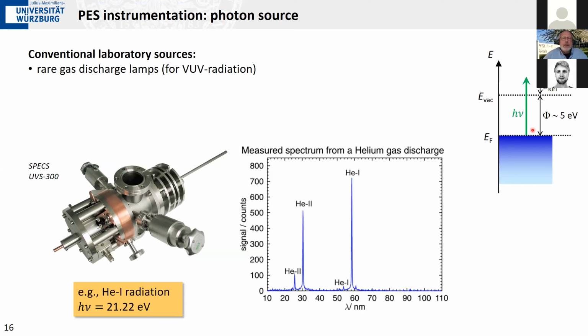And the easiest way to create such radiation is by exciting helium gas, either by electron bombardment or by microwave excitation, or by just applying a high electrical field. And then you can excite a 1s electron into a 2p state in helium, and then this state will relax again and emit at a frequency at about 21.2 electron volts. This is done with a helium rare gas discharge lamp, as is shown here.